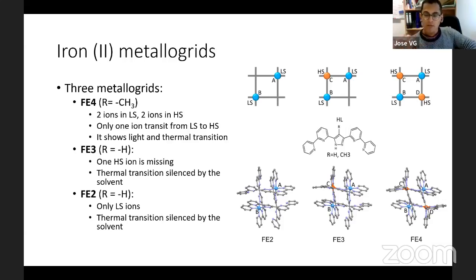We also have a similar structure where one of the high spin metal ions is missing. And finally, we have another grid-like structure when both high spin ions are missing. However, if you look at the structure with only 2 low spins, you will see that there is nothing connecting the low spin ions.